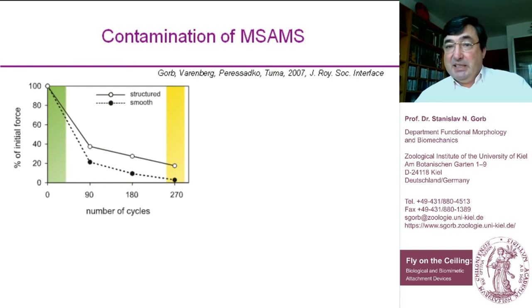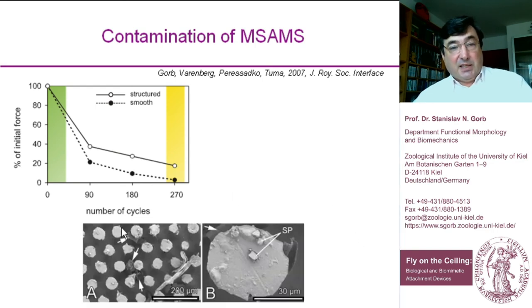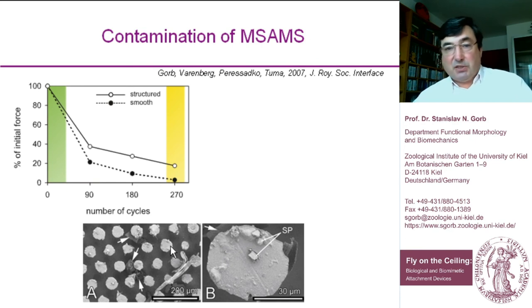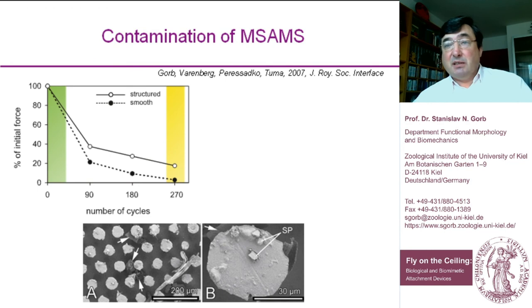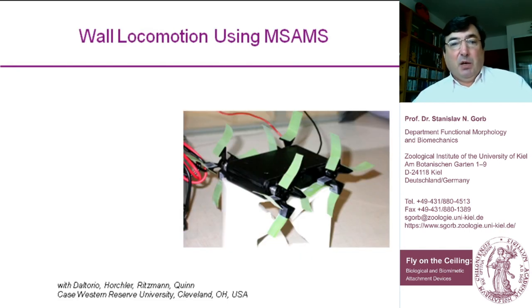What about contamination? If you make an experiment with structured material and smooth material, you see that the structured material does contaminate, but not as fast as smooth material — a very important point. The explanation is simple: environmental particles are first packed in between the features, while the little plate-like head structures remain exposed to the environment and stay clean for a while. As long as the heads remain clean and dirt is packed between features, sufficient adhesion is maintained. Even if the material is completely contaminated, you can wash it out, and after about 300 washing cycles the full adhesion returns — because it is not based on chemistry but on structure and contact geometry.